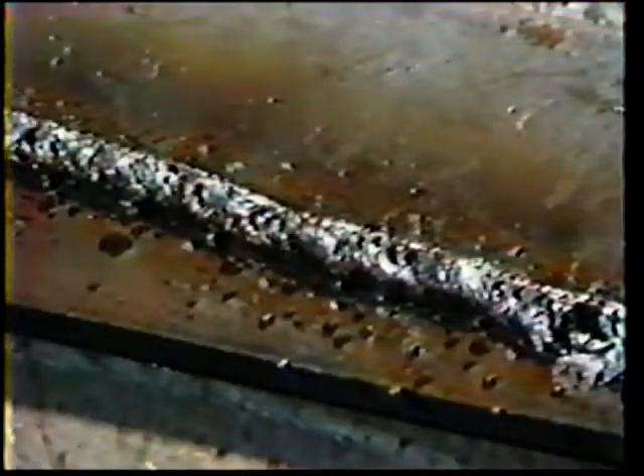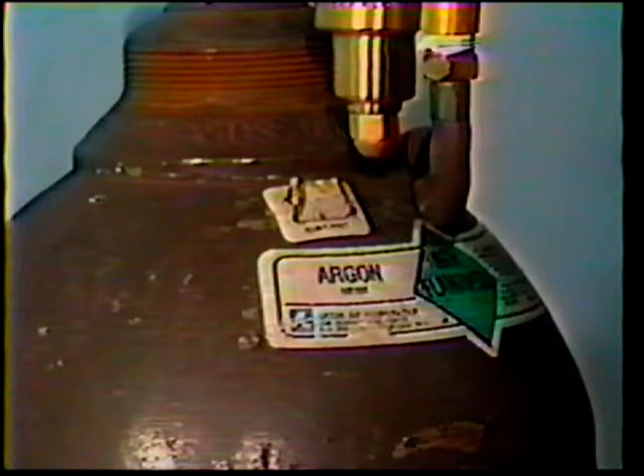Argon produces excellent results on non-ferrous metals, but yields poor results on ferrous metals such as low carbon steels. Welding grade argon is a common economical gas that is 99.5 percent pure. Flow rates can be reduced because argon is 38 percent heavier than air. It aids in starting the arc and creates great surface cleaning action when operated with direct current electrode positive, or reverse polarity.